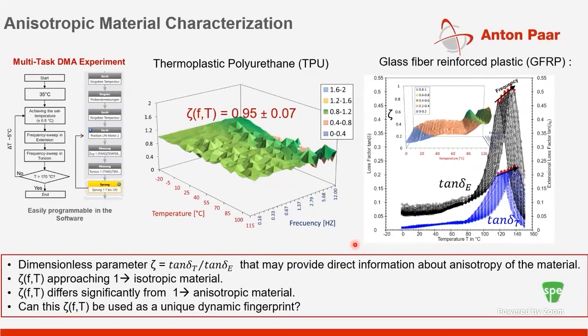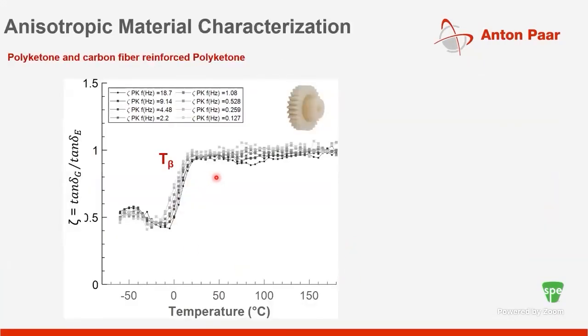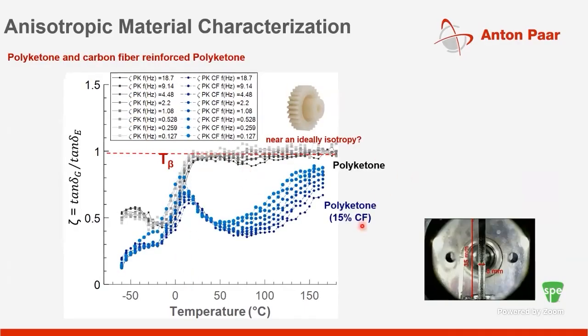Let's go back to our polyketone example, which I talked about earlier. When I use the zeta factor in this case, a factor close to 1 is obtained, at least for data above the glass transition, for the pure polyketone case. But when I use the carbon fiber reinforced polyketone, the data both below and above the glass transition deviates—zeta deviates from 1—which clearly shows the anisotropy present in the material.